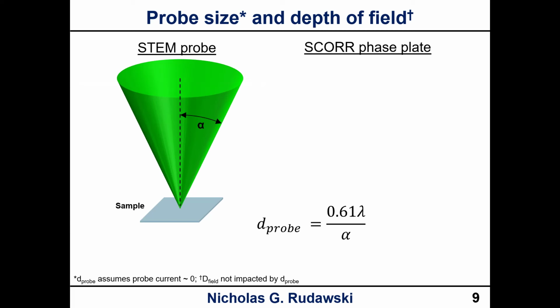But then the other parameter is the depth of field. The depth of field is also proportional to the reciprocal of alpha, but you're also multiplying by the physical size of the pixel in the STEM image. So if your pixel size is 1 nanometer, that's what you would put there for x sub pix.